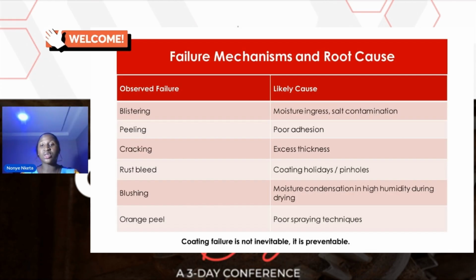So we see a lot. These are a few of what we see almost every time on the field. So you may have blistering. This is actually very common, very, very common. And what are the causes? Moisture ingress, salt contamination from that system. Then peeling. That one is just quite obvious. Poor adhesion. And sometimes when you apply a coat without a primer for a product that requires you to prime before you apply the product. If you don't prime, you're likely to get peeling.